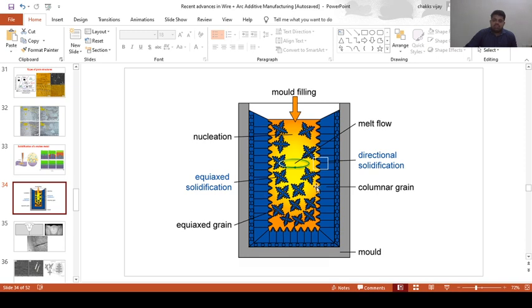And here you can observe, especially in this kind of normal casting process, in the die casting process, this is a die. In the die, the heat dissipation rates are much faster. Due to this, the solidification will be more rapid, and it will begin from here. Here you can observe some small finer grains, here some coarser grains, and here some equiaxed structure.